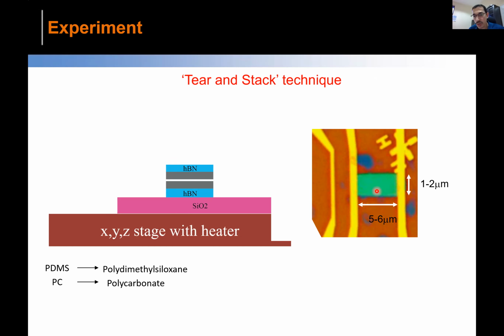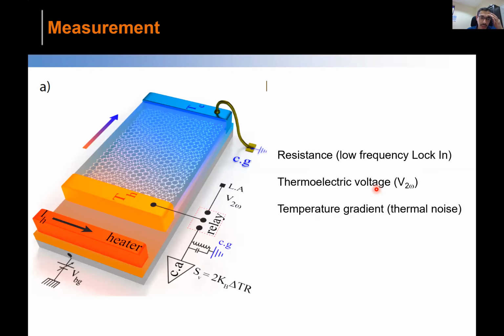So this is what the device looks like. What you see here is the magic twisted bilayer graphene. The color you see is from the boron nitride, this is the boron nitride encapsulated sample. There are two contacts you see here, and there's a heater. As I told you, I have to create a temperature gradient across this sample. By passing current, this heater will create a temperature gradient across the sample, and I can measure it. So this is how the actual measurement schematic looks.